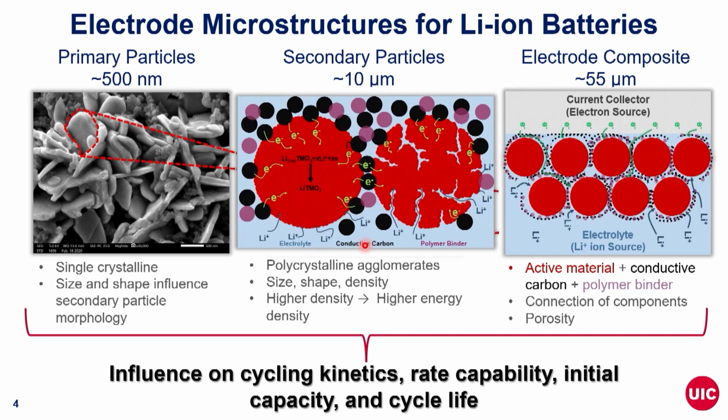So if we look at the different processes within the battery, from the previous slide, we have two processes: the lithium-ion flow and then the electron recombination or charge compensation. These have different pathways in these microstructures. The electrons flow through the solid component, so that conductive binder matrix, into the solid crystal structure of the cathode or our anode structure. The lithium ions alternatively flow through the pore network through the electrolytes.